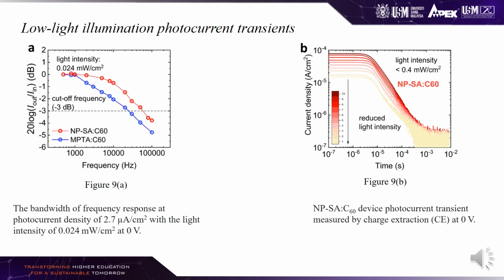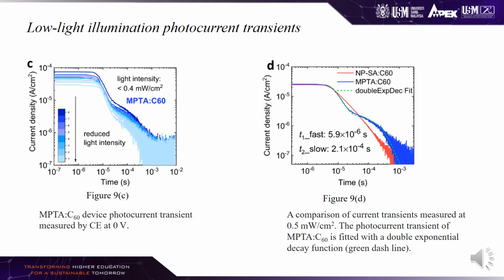This slide shows the low light illumination photocurrent transients. Figure 9a shows the bandwidth of frequency response at photocurrent density of 2.7 microampere per centimeter squared with the light intensity of 0.024 milliwatt per centimeter squared at 0 volt. Figure 9b shows the NPSA carbon-60 device photocurrent transient measured by charge extraction, CE, at 0 volt. Next, figure 9c shows the MPTA carbon-60 device photocurrent transient measured by CE at 0 volt. And diagram 9d shows a comparison of current transients measured at 0.5 milliwatt per centimeter squared. The photocurrent transient of MPTA carbon-60 is fitted with a double exponential decay function, green dashed line.